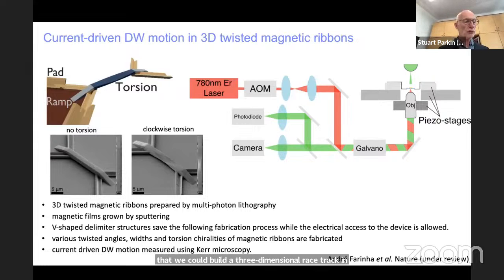Another project, which again, I don't really have too much time to discuss, is where we introduce a geometrical torsion into a racetrack. This is more for understanding the competition between spatial chirality, if you like, and the spin chirality within the domain walls. So here, this is a project again by another PhD student, Andre Farinha. And what he did, he built a three-dimensional printing system using multiphoton lithography and using super resolution techniques. So he could introduce a polymer into the microscope and cause polymerization and therefore form a structure with a pixel size of about 50 nanometers, which is many times better than any commercially available lithography printing system.